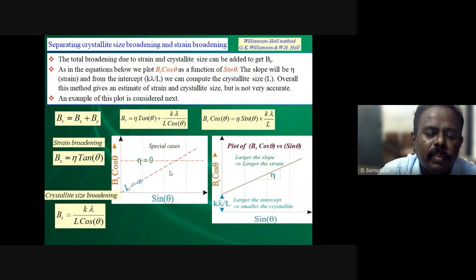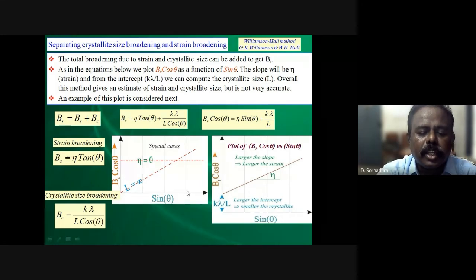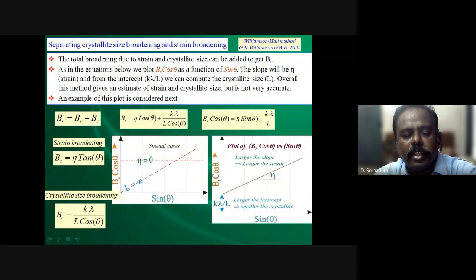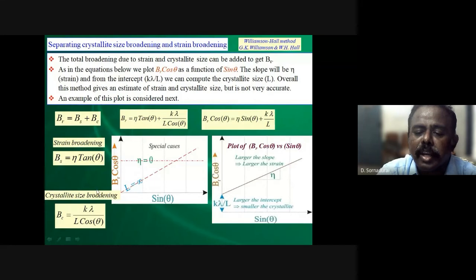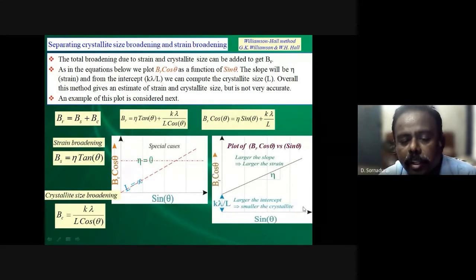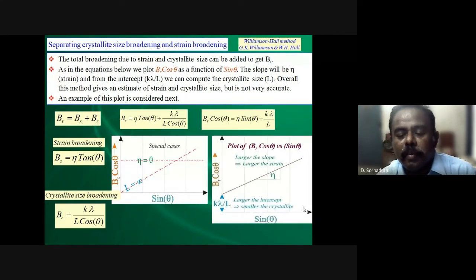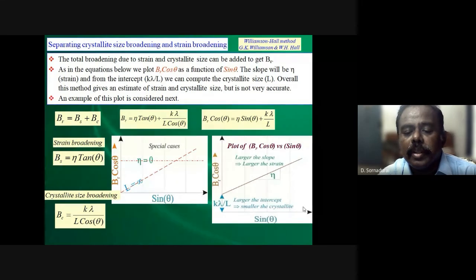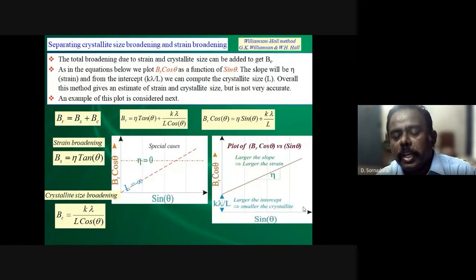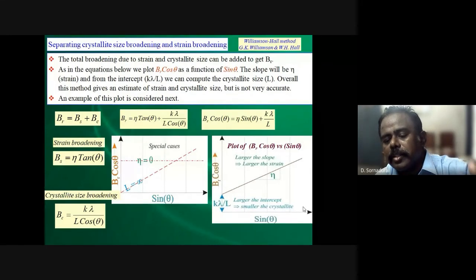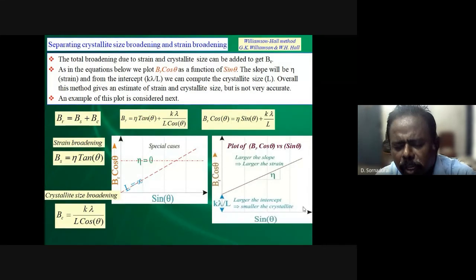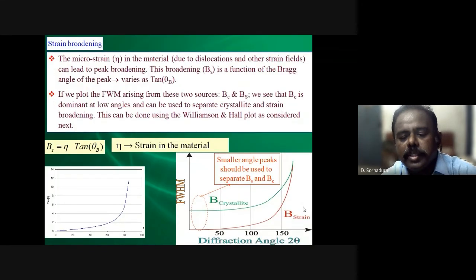So generally we cannot use this formula just like that, but you can take beta r cos theta by sin theta within a range, differentiate the crystalline size and the strain, and get the information from curve fitting. So far we have discussed X-ray generation, detectors, how to deconvolute the peak, and how to extract information like strain broadening and crystalline size broadening. All these things we have discussed up to now.